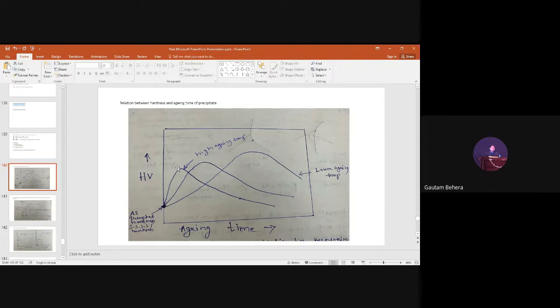And the conclusion we can get is, if we keep a relatively low temperature, we can get maximum strength and hardness, but the aging time will be more because this is the peak hardness value here. But if you keep a high temperature, the peak value is this one, which is lower than this value. And this is happening, you understand, because if we maintain a relatively high temperature, the rate of precipitation is increasing and the peak hardness is this one.